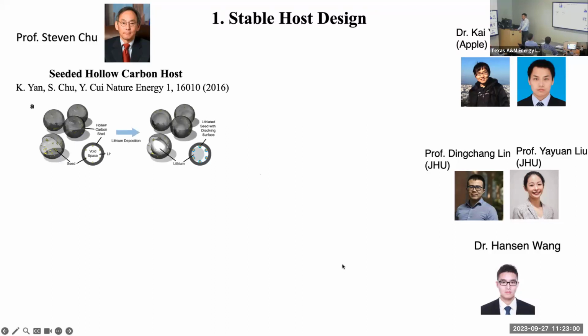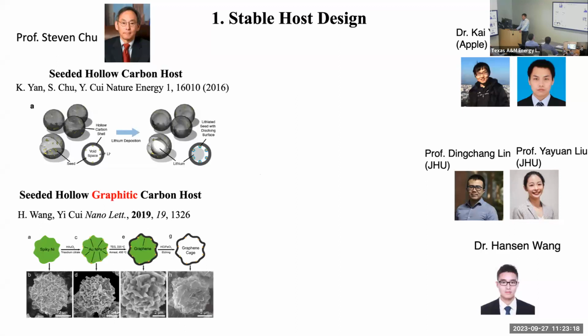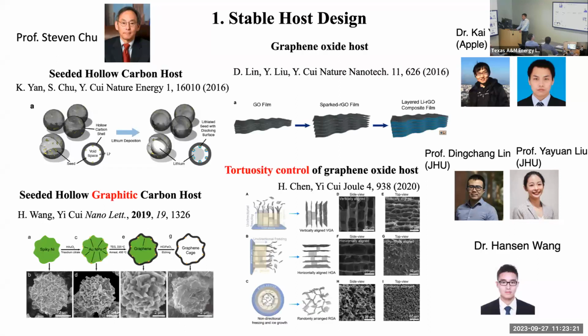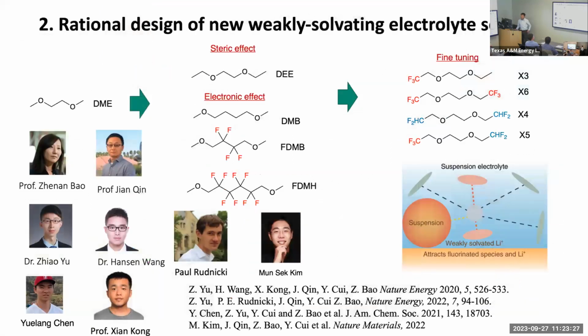So we published a concept of stable host by designing this hollow carbon and depositing lithium inside the hollow host, hosting and guiding the lithium deposition. I'm going to tell you a little bit more. And then we have been through a whole series of host designs, so I don't need to bother you because I need to go deeper. And also in parallel, we understand the interface needs to be very stable. The metallic lithium with organic electrolyte. We need a new type of organic electrolyte.